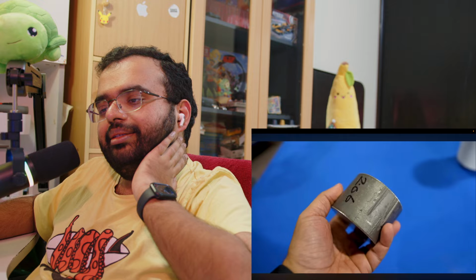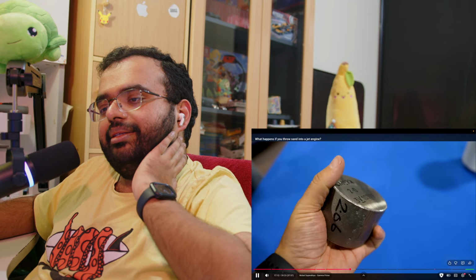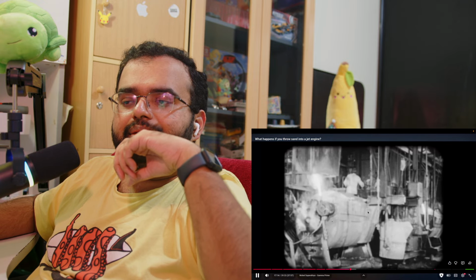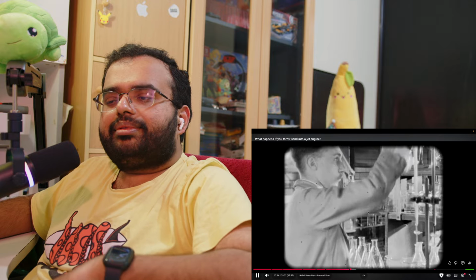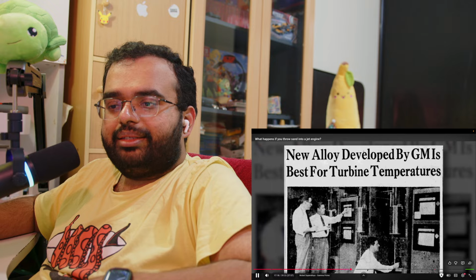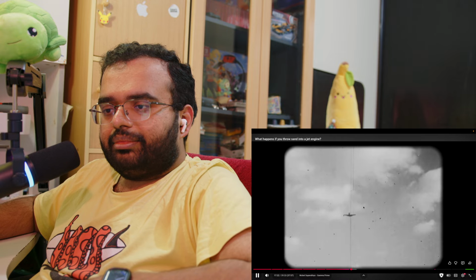The first nickel alloys used in jet engines were developed in the 1940s. By adding chromium and cobalt, engineers created alloys that could handle 800 to 900 degrees Celsius, around 100 degrees hotter than the steel used before. And these alloys could keep their strength for thousands of hours, a 10-fold improvement in life. But the real breakthrough came when they added a touch of aluminum.